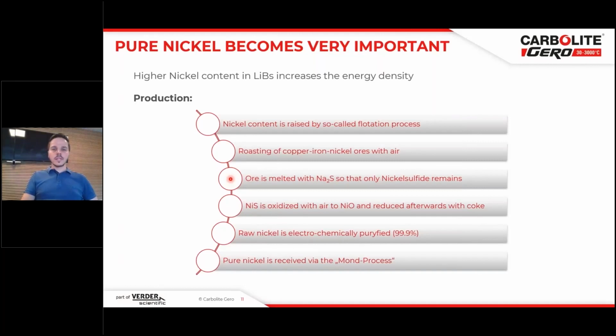This nickel sulfide is then oxidized with air into nickel oxide and reduced afterwards with coke. So a lot of coke is put into this process to get a nickel with a, let's say, purity which is okay. And the raw nickel is then electrochemically purified to about 99% approx, and to reach an even more pure nickel, which is very important. What we learned at the first slide from Tom, he said we need very, very pure materials for a long, long lifetime of the materials. It is then received via the Mond process.